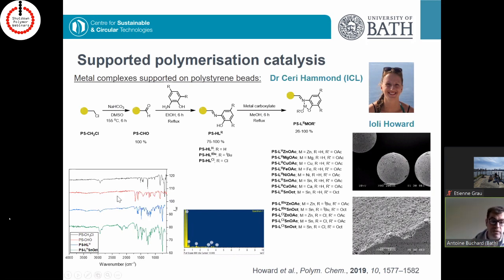One of the methods we use is IR, because you can really easily follow the vibrations of various groups, including this imine group here. And then once the metal is coordinated, especially because we focused on carboxylate, acetate, octanoate, this type of stuff, we could also clearly see those vibrations in the IR. We did characterize those beads using EDX as well, and also visually by SEM. We could see that we had some nice beads. When we cracked them, you could see a clear difference between the core of the bead and the surface, which